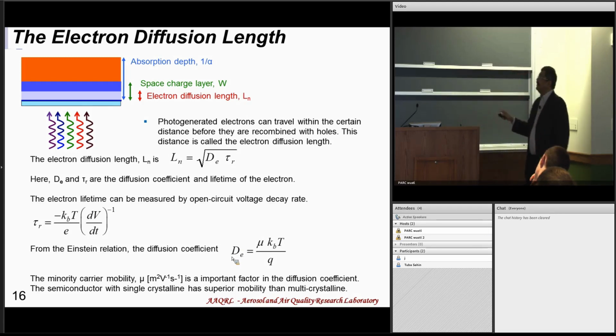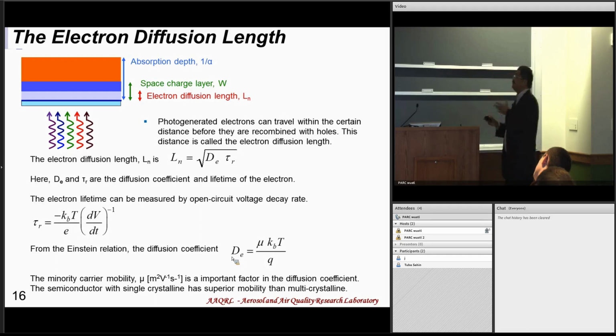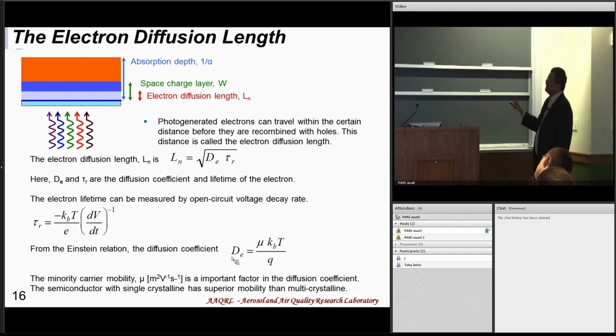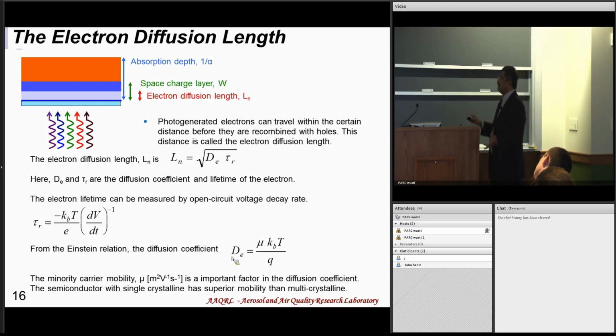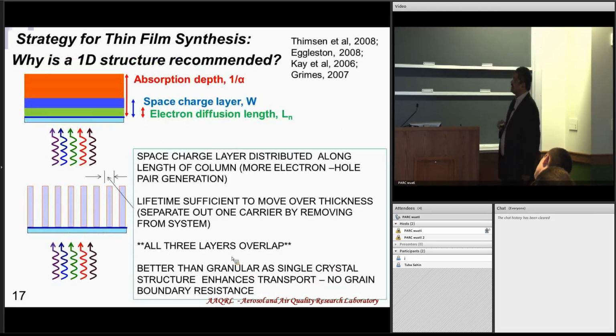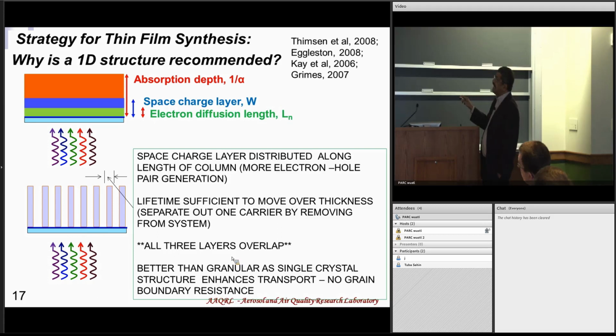One can get an estimate of this diffusion length. So again, remember the space charge layer and then this electron diffusion length, and this is just an illustration showing you that. This might be important, but if the electron can only diffuse a certain distance before it's lost or recombined, it's of no use to us. So we need to match this out. So I put all of this together. In a flat structure like this, the absorption depth, of course, I need to exceed that, or at least have that, to make sure my photons are absorbed, right? But then within that, this layer is important, and I just discussed this layer.